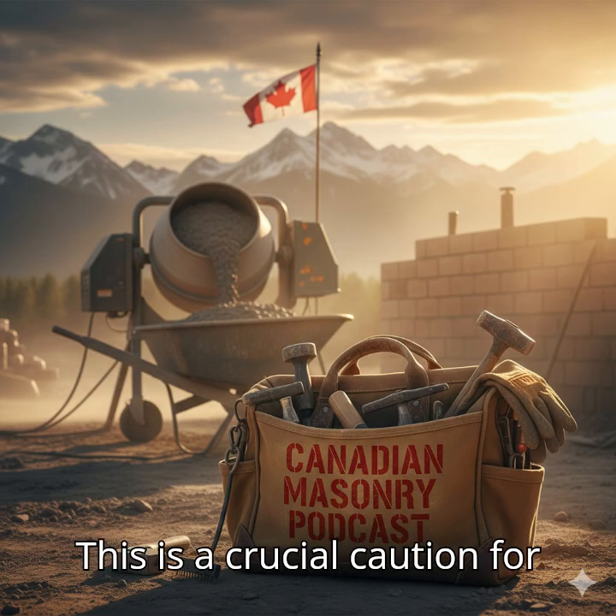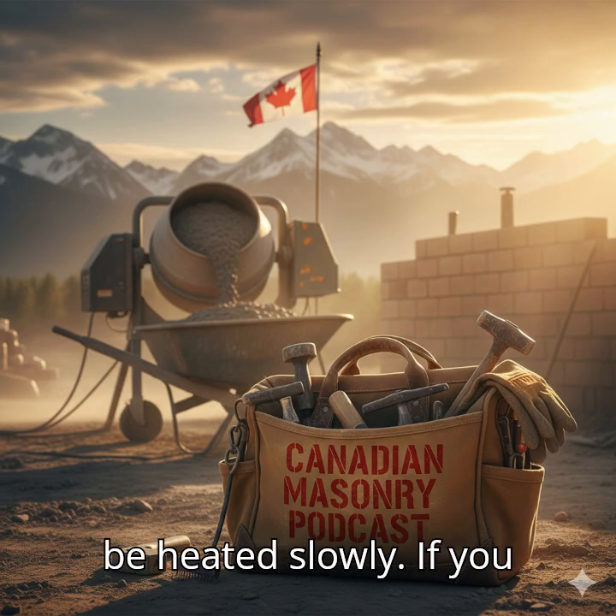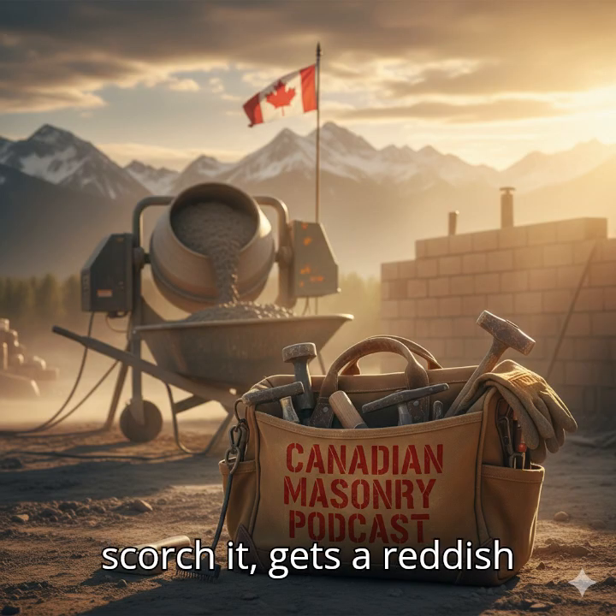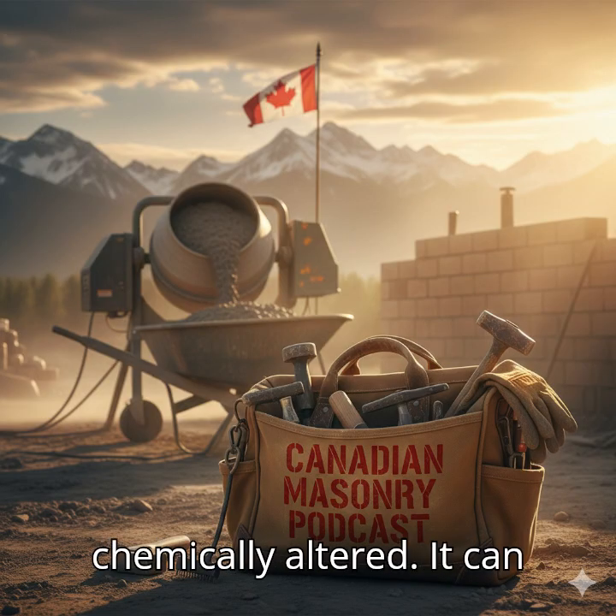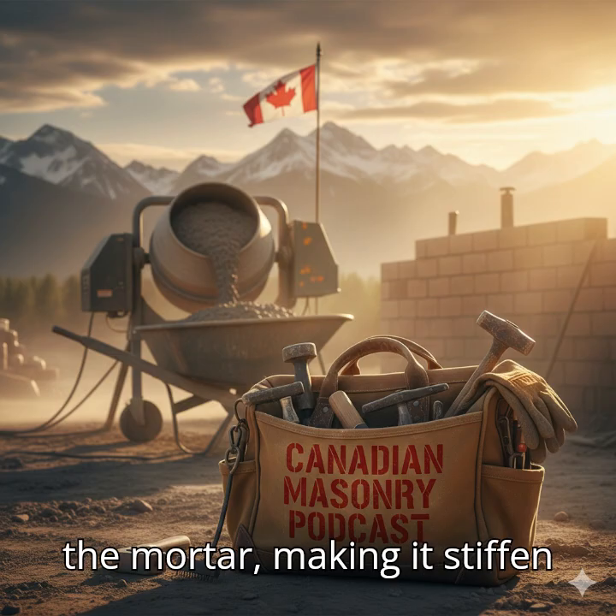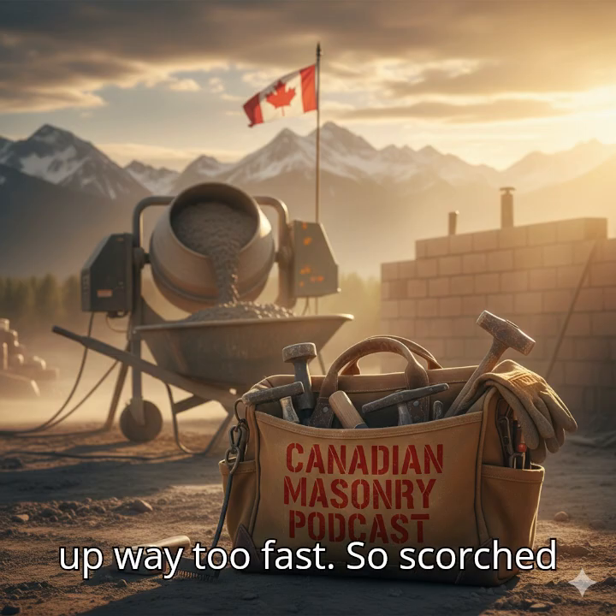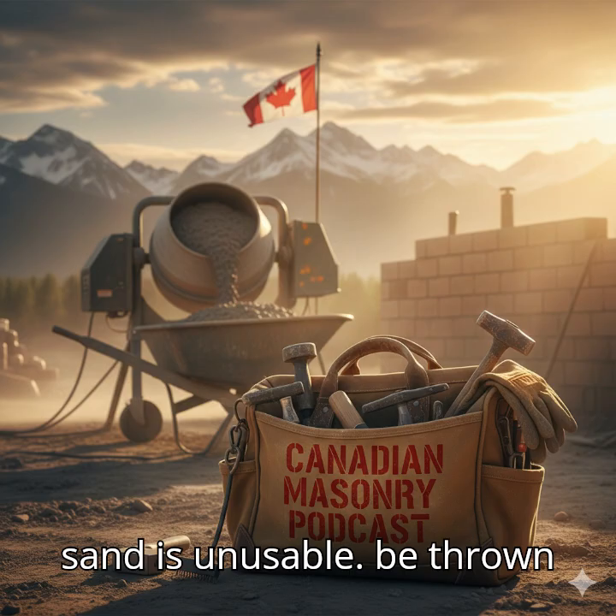This is a crucial caution for every apprentice. Sand has to be heated slowly. If you scorch it, it gets a reddish, burnt tint, and it's chemically altered. It can accelerate the set time of the mortar, making it stiffen up way too fast. So scorched sand is unusable. It has to be thrown out.